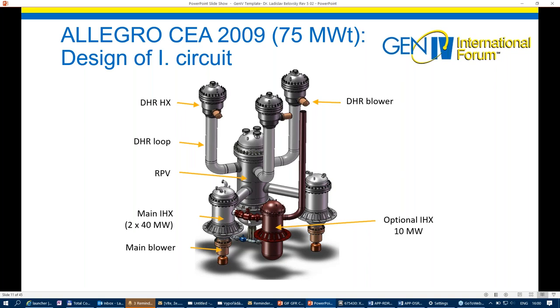We have here in the central part the reactor pressure vessel, the two primary loops with the helium water heat exchangers. Here in the bottom we have the main blowers. Here we have three decay heat removal DHR heat exchangers in the top, using the chimney effect in the case of primary natural circulation. Here you can see the decay heat removal blowers, and this red component is an optional gas heat exchanger, which was proposed to use the heat from the primary circuit for technological purposes.